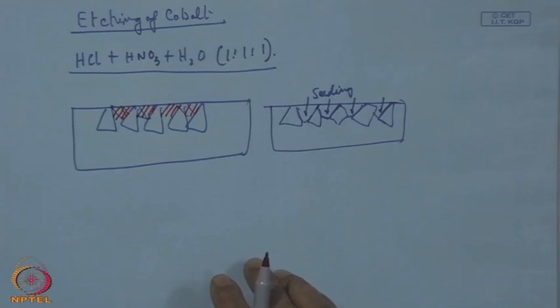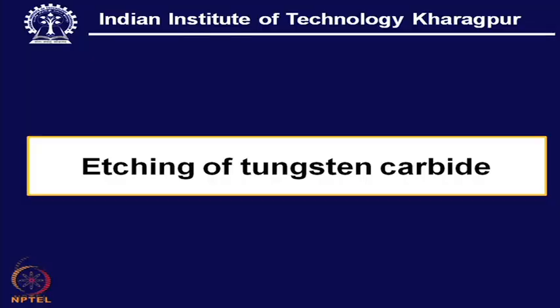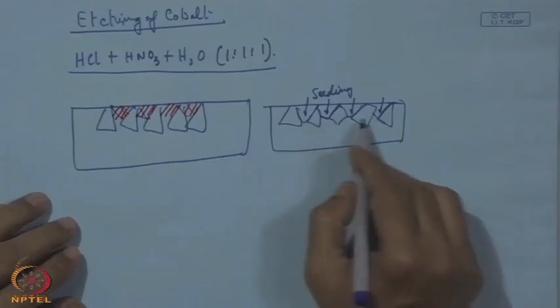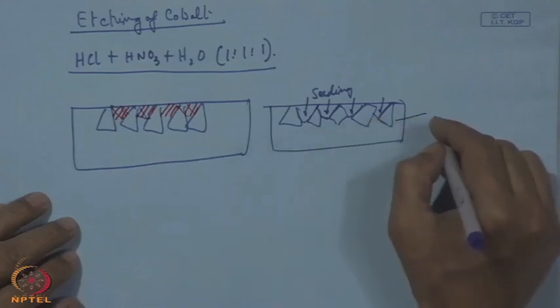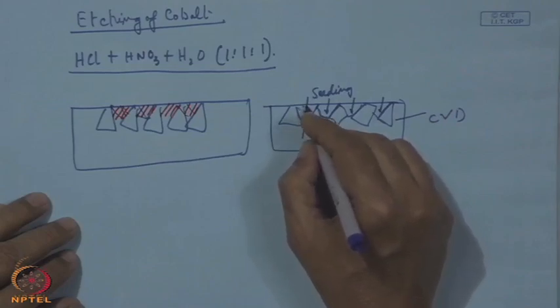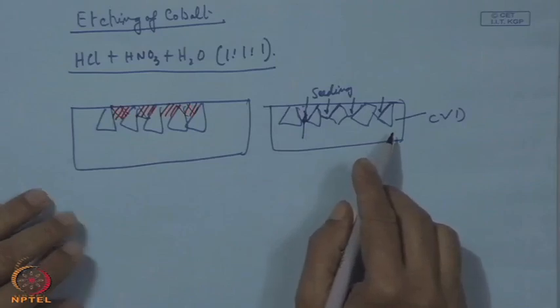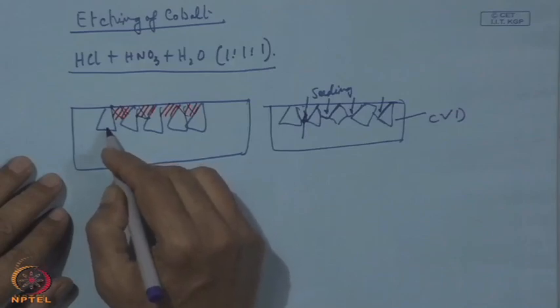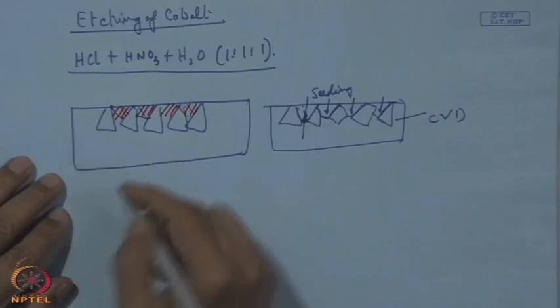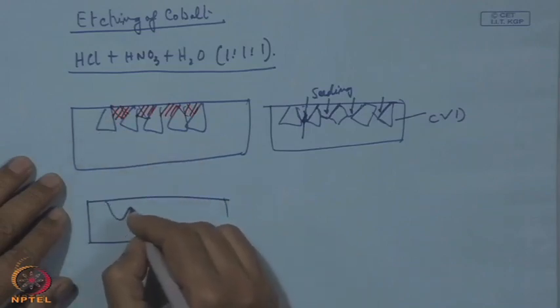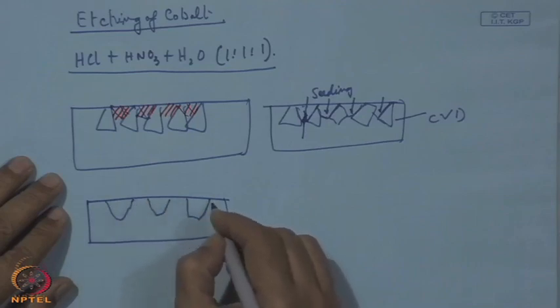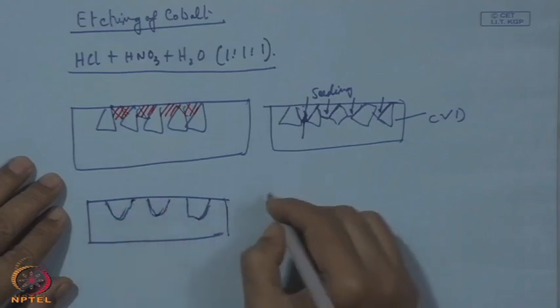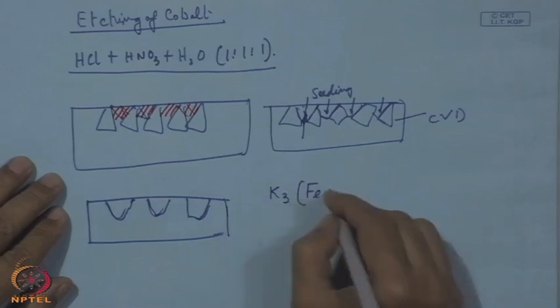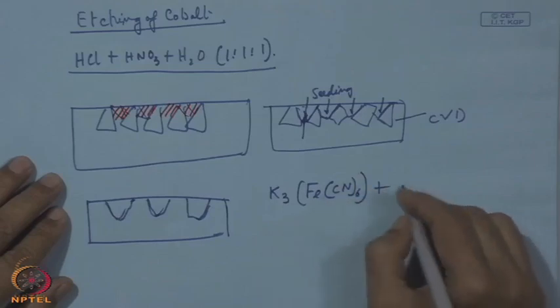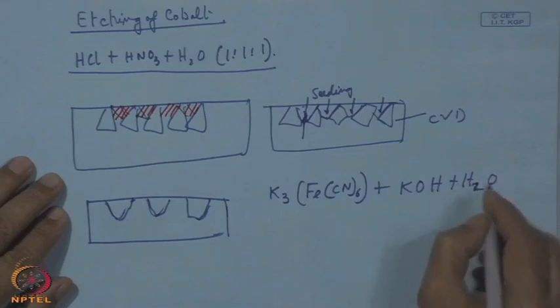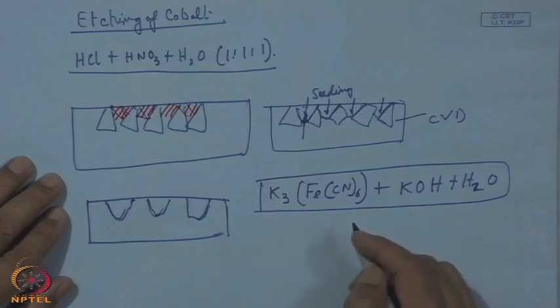So, this is one way of doing the thing, but there is another school of thought, etching the tungsten carbide. The whole idea here is that though we are etching cobalt, it may not be very useful, because during the high temperature CVD, this cobalt can also diffuse and come to the surface, and the whole purpose of etching the cobalt is lost. So, we can also etch tungsten carbide to leave these cavities. That means in this case, this tungsten carbide will be etched, leaving large cavities, and this can be done by one solution called K3Fe(CN)6, Murakami's reagent, and then we have KOH plus H2O, this is the standard reagent for etching the carbide, and that can be intelligently used for removing this.